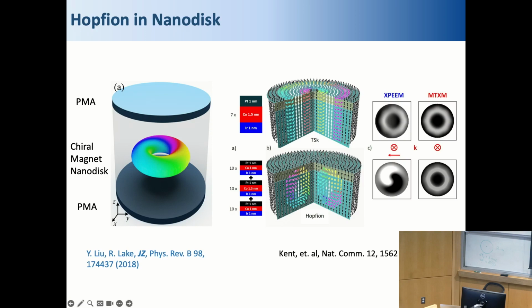I always believe that a stable hopfion, in a single crystal, must be a multi-Q state. It must be a multi-Q state. But the question is, how shall we distribute these Q directions? And how can we find a material realizing this multi-Q state? This is the problem. It must be a multi-Q with the star having more than 3. More than 3. And they must be non-coplanar. Non-coplanar. Yes.